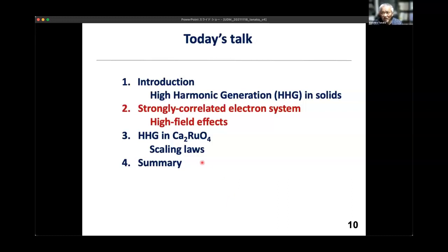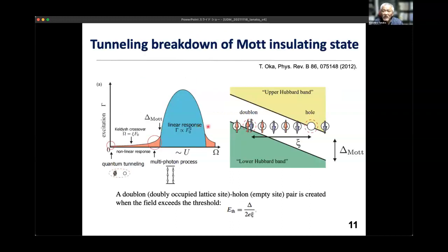All right, so I'd like to review a little bit what's happening in strongly correlated electronic systems under strong field. Professor Oka predicted tunneling breakdown of the Mott insulating state by theory. This is the frequency axis, and he fixed the field strength F0. When we change the frequency, around here we can see the linear response, which is a resonant region. But in the non-resonant region below the band gap, we can see some Keldysh crossover, and below this energy we can expect the quantum tunneling picture to be valid. He predicted doublon, a doubly occupied lattice state, and also holon,